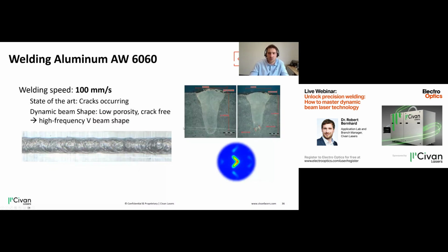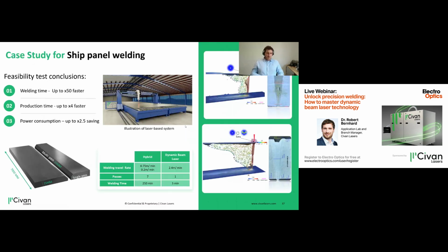So this actually means we can weld this 6000 series aluminium up to 100 millimeters per second, and usually there are cracks occurring as well as porosity. But if we use our boomerang shape or V-beam shape, we can reduce the porosity, and because it also adjusts the flow and the melt pool solidification rate, we are reducing the solidification cracks. But this is not all.